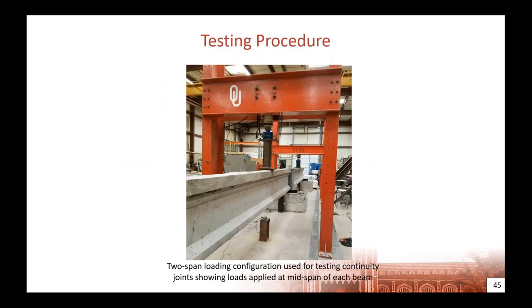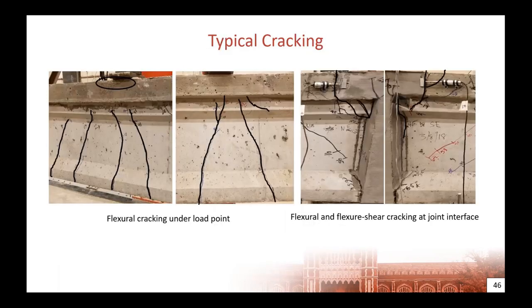This is a picture of that two-span beam system being tested for negative moment. So it's supported here at the center, single point load at mid-span of each girder to apply a negative moment across that joint. And again, this specimen was designed to develop the full strengths of the beams. So we were looking for failure in the beam, not at the joint necessarily. And so we had typical cracking in the beams that would include flexural cracks underneath the joint and then underneath the load. And as we move to the connection, we would see flexural cracking starting at the top and then flexure shear cracking coming out away from the joint and moving back toward the joint.